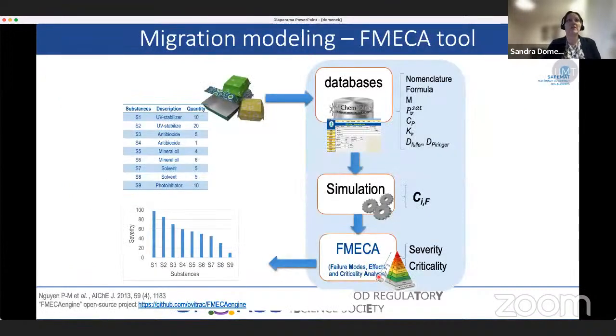In this respect, we developed inside the SafeMat project a comprehensive tool for migration modeling, which is called the FMECA tool, and it is an open source project. You can find it here at this link, and you can copy it and work with it. This simulates the migration of any type of surrogate inside a food contact material, taking into account either existing databases of known diffusion coefficients or known partitioning coefficients, or very robust physical extrapolations of these different transport parameters, always ensuring an overestimation, because the overestimation is giving us the assurance that we are on the safe side.